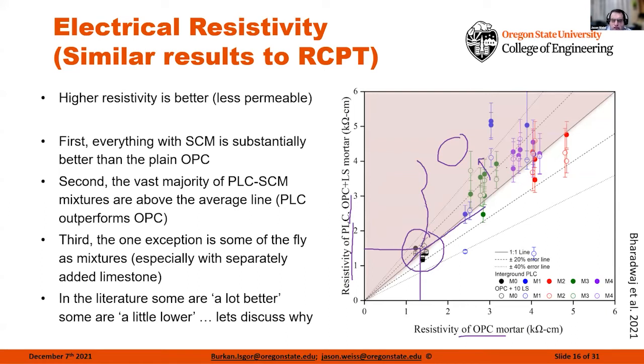We also notice that we see increased benefits when we have limestone in the system, not because we're decreasing the porosity, but primarily because we're decreasing the pore connectivity, making it harder for ions to move through the system. So we're actually making smaller and tighter pores in these systems that make it harder for the ions to flow.